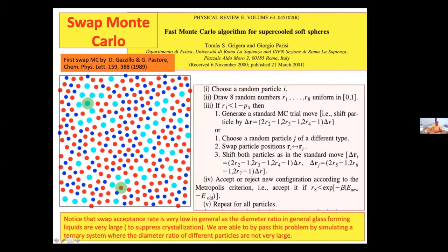So the idea is that this is very similar to the Monte Carlo method that they discussed, but you add another step. So as usual, while choosing a random particle, you either displace it and then accept that move by some Metropolis algorithm, or you choose an opposite, different type of particle and swap their position. So if you look at this cartoon, these two particles are chosen which are opposite in color. So they are basically different types of particle. And then you swap their diameter or their identity or their positions. Any of these, they are all equivalent moves. And then you accept this move according to a similar Metropolis algorithm. And this step you continue to do.